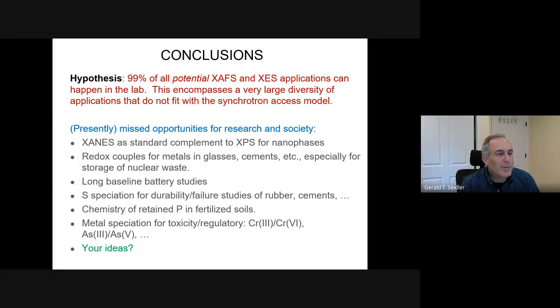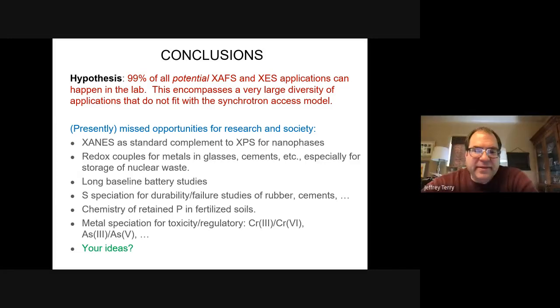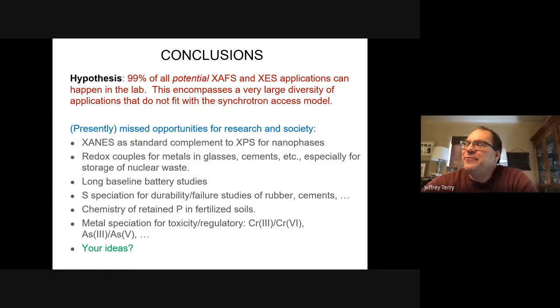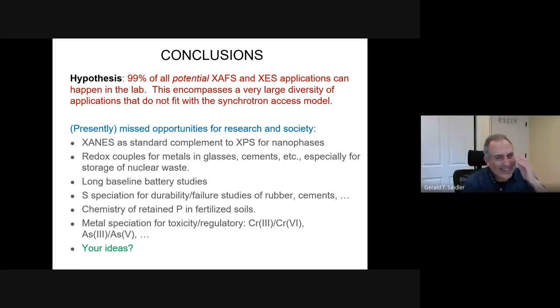But then maybe only 1% of the X-rays are even being absorbed. And then all of a sudden your fluorescence count rate is way down and the measurement's going to take a very long time. So I think there are going to be special cases where it's possible to do fluorescence in the lab, but in general it's really not advisable. It's not something I've done with my equipment. All right, thank you. The XES, on the other hand, you can do on thin films if the thin film is concentrated, but that gives you different information. Yeah, we were hoping to do that right before the coronavirus hit.